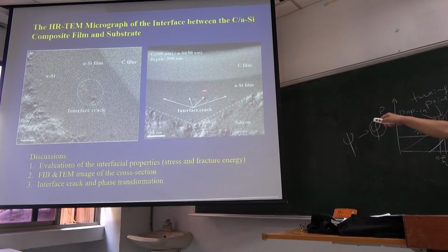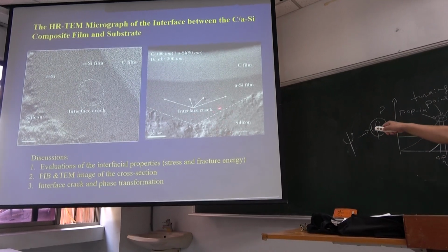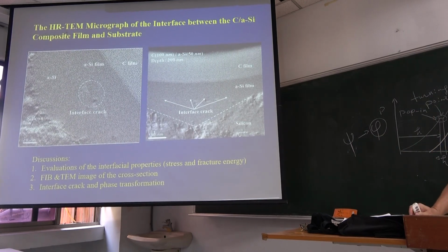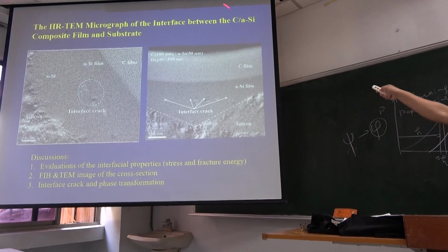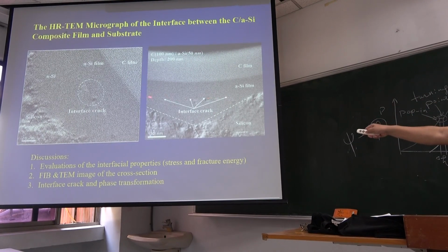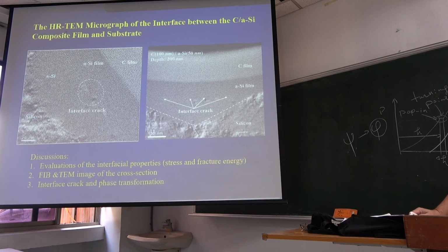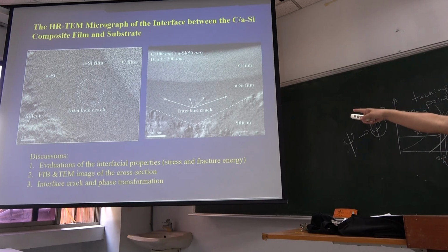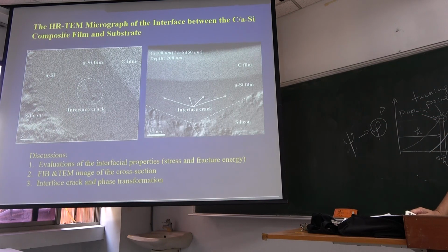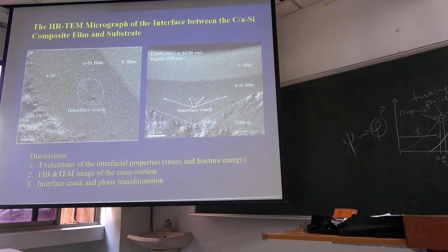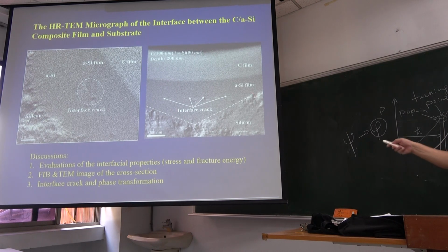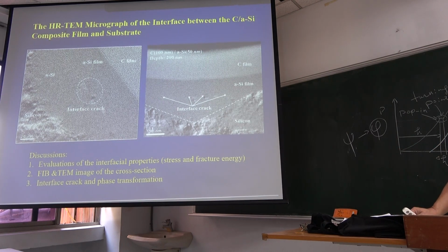This film originally was connected with the single crystal substrate, but now it is separate. So after the load is removed, you'll find that there exists a nanoscale crack over the interface, like this one. The last one they showed was a dislocation or something. But on the engineering scale, when we observe it by TEM or SEM, we find it is actually just a micro or nanoscale crack.